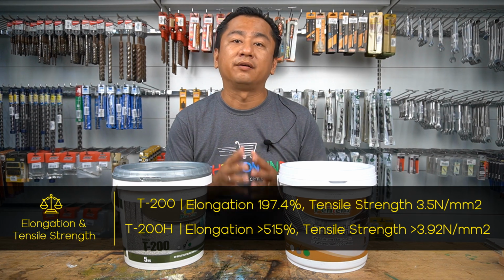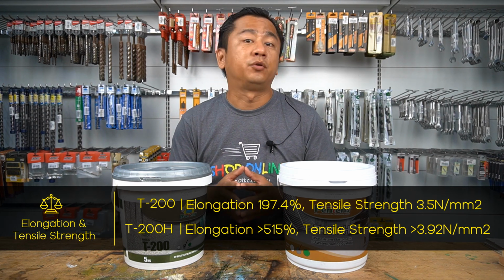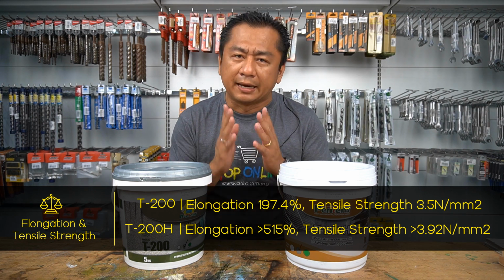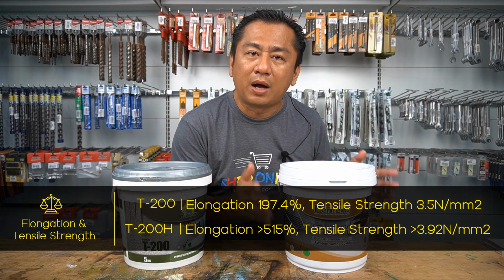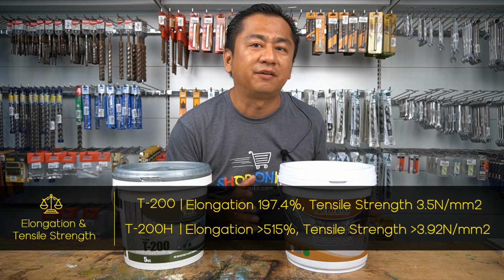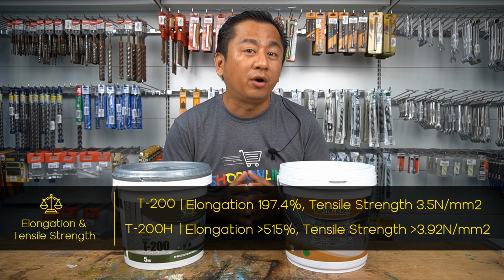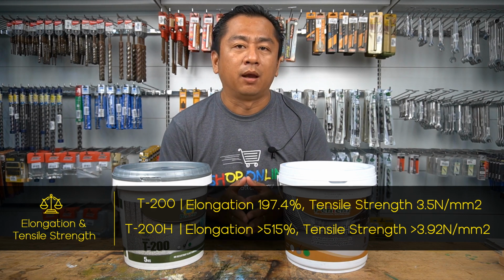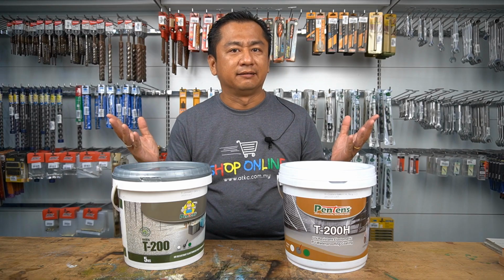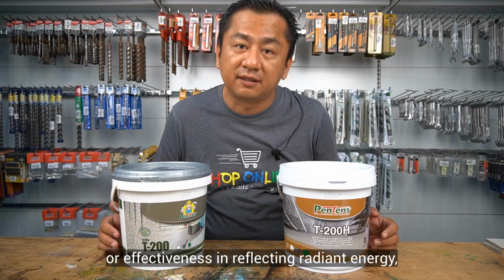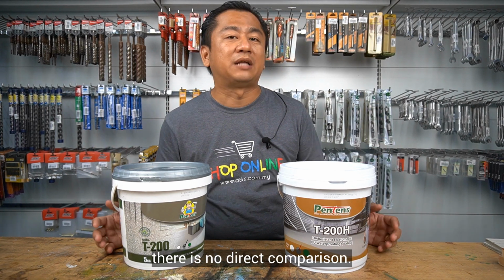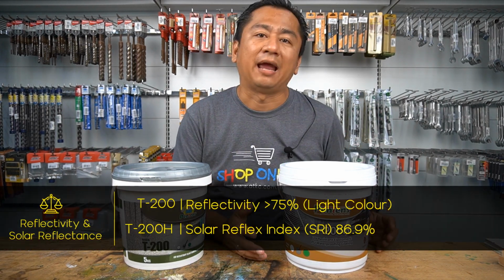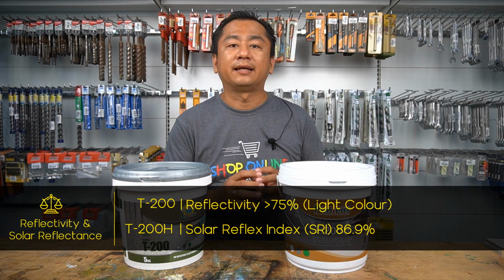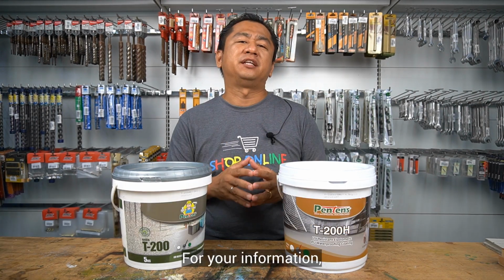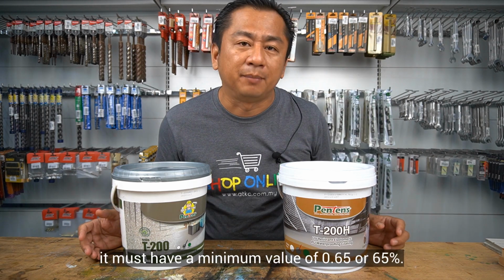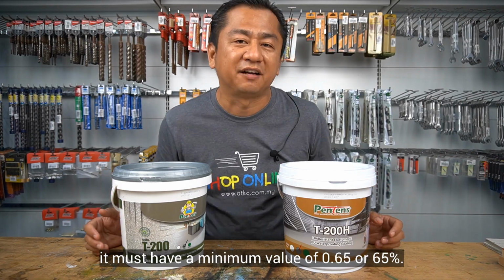T200 has elongation of 197.4% with a tensile strength of 3.5 Newton per millimeter square. Now, listen carefully. Pentens T200H has elongation of more than 515% with a tensile strength of more than 3.92 Newton per millimeter square, which is higher. How surprising! In terms of reflectance or effectiveness in reflecting radiant energy, there is no direct comparison. Pentens T200H emphasizes on SRI or solar reflect index with more than 86%. For your information, for a cool roof performance, it must have a minimum value of 0.65 or 65%.